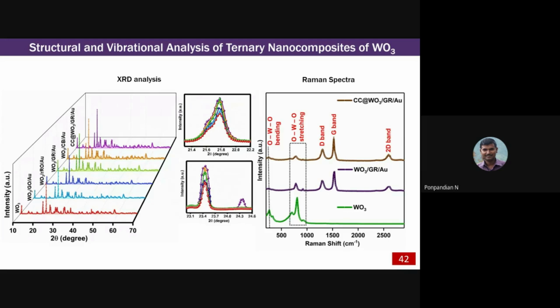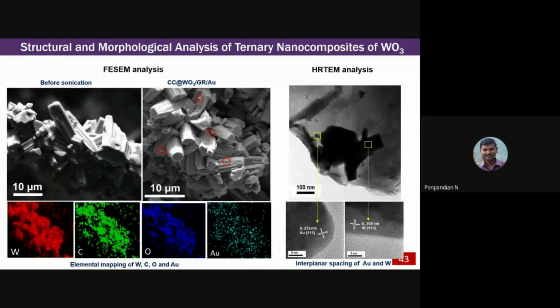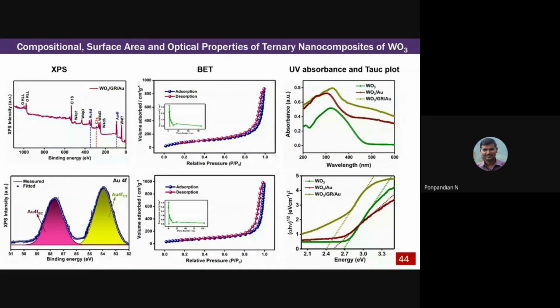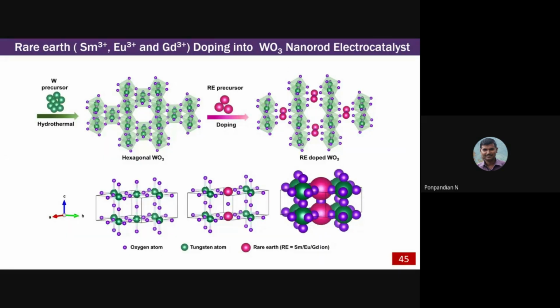These are some more characterizations of this particular material. This is a ternary nanocomposite. I already mentioned this: tungsten oxide, graphene oxide together with gold nanoparticles. This is the morphological structure of that material. Next, this is the surface area. We have measured the surface area of all those samples, and the composition and all those things we have measured through XPS, PL as well as the visible absorption spectrum. Now the next step, this is the first step we have done. There is a first kind of sample, starting from tungsten oxide, with graphene and gold.